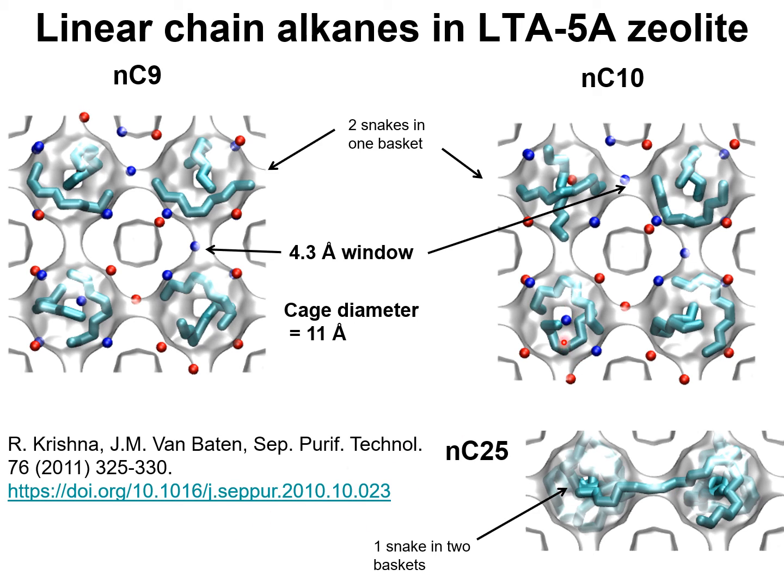Therefore, for mixtures of, say, NC10 and NC25, at pore occupancies close to saturation, entropy effects will favor the shorter NC10 molecule rather than the most strongly adsorbed NC25.